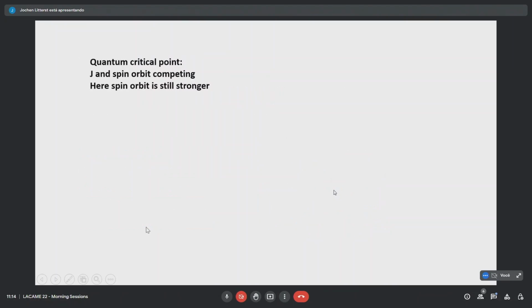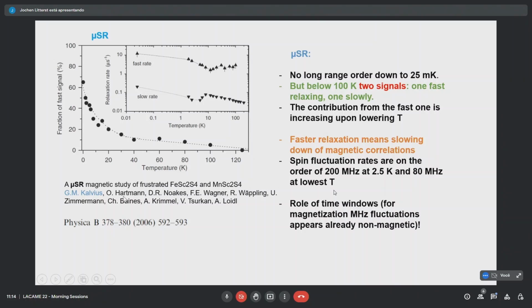Now, we have looked at that again. Just after that, there was a muon SR experiment. Actually, one doesn't see magnetic order, but notably below 100 Kelvin, two signals were found. One was fast relaxing, one was slow relaxing. Fast relaxing means we have a slowing down of magnetic correlations. So we have a mixture of two scenarios. In part, we have fluctuation rates which are relatively slow, in the range of 100 megahertz, even at lowest temperatures. And the other part is fluctuating fast. So we have a kind of separation within the material.